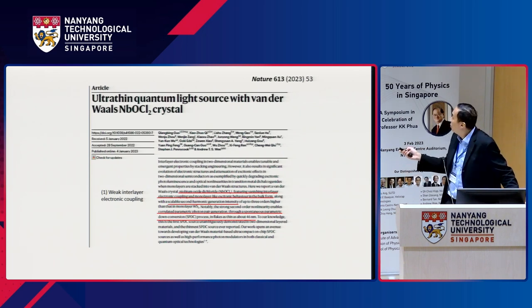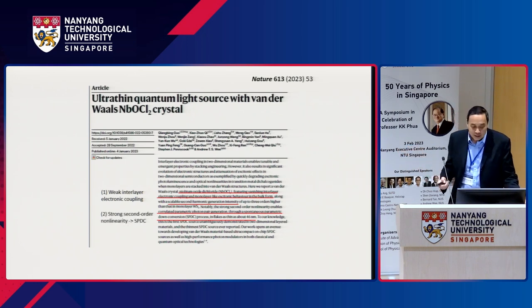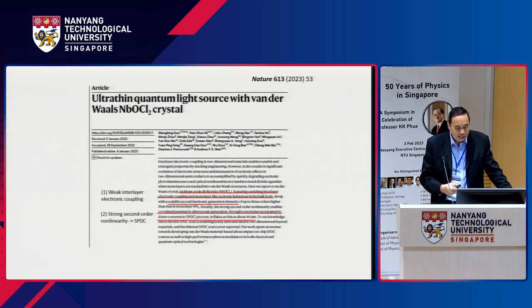The other property which makes it different is that it has a very strong second order non-linearity. And that enables correlated photon pair generation, which our collaborator managed to do some measurements with and showed SPDC in this material. So this was certainly an interesting material to work with. But I must say that this sort of work requires a lot of multidisciplinary collaborations with a lot of people having different sorts of techniques and not just one sort of technique.